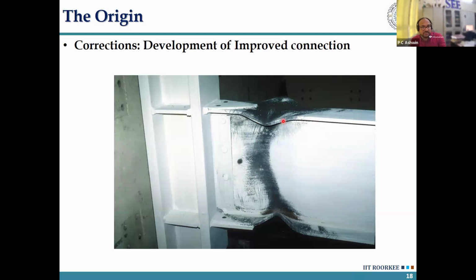So the natural thing to do is, how can I delay this local buckling in a member? Whenever local buckling happens, when I look at the hysteresis curve or the load deformation curve, whenever instability occurs, the energy dissipation capacity drops drastically. So as an engineer, you are like, okay, my rule was strong column, weak beam. The plastic hinges should form in the beams itself. That is forming. But this local buckling is creating a problem for me because it's an instability. So how do I delay it? That is what we do with the compactness criteria, or the b by t or d by t criteria that we use.